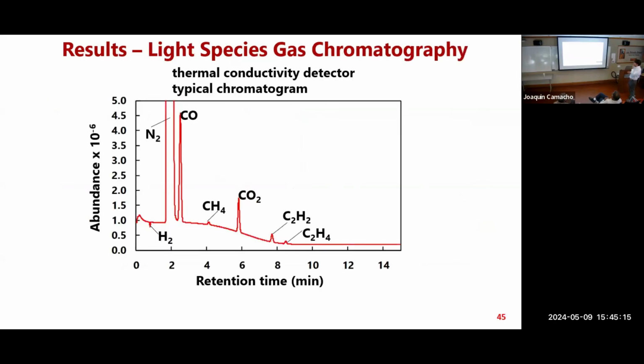So we do have quantitative measurements of the gas phase. What you do is feed this into the gas chromatograph mass spec. What the gas chromatograph part does is it separates a mixture. So this is what we get from the gas chromatogram. You feed it into this chromatography column, and over time each of these molecules separates, and it detects each one as it comes out. So it detected that we have some hydrogen coming out early and some nitrogen. So these are the species in the gas phase that we can see, and we have since quantified these in terms of our calibration.